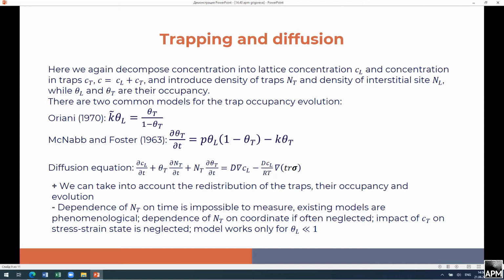So there are two common models which are used widely for the trap occupancy evolution. The first one is quite bad, because you can see that even though we have a time-dependent concentration and therefore time-dependent occupancy of traps and interstitial sites, we don't have any time dependence in the model for the trap. So if we have some changes in the interstitial occupancy or trap occupancy, the other occupancy will change in one moment, which is actually not a physical thing.